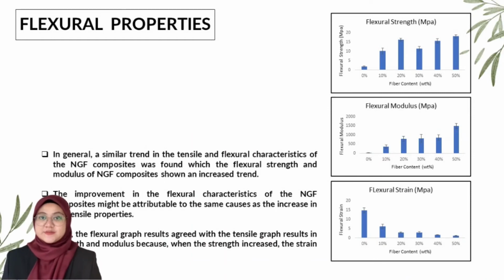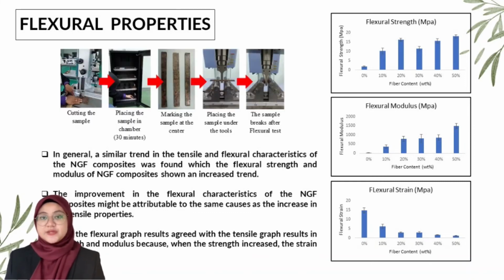As for flexural properties, generally a similar trend to the tensile characteristics was found for the Napier grass fiber composites, where the flexural strength and modulus showed an increasing trend. The improvement in the flexural characteristics might be attributed to the same causes as the increase in the tensile properties. Thus, the flexural graph results agreed with the tensile graph results in strength and modulus, because when the strength increases, the strain will decrease.